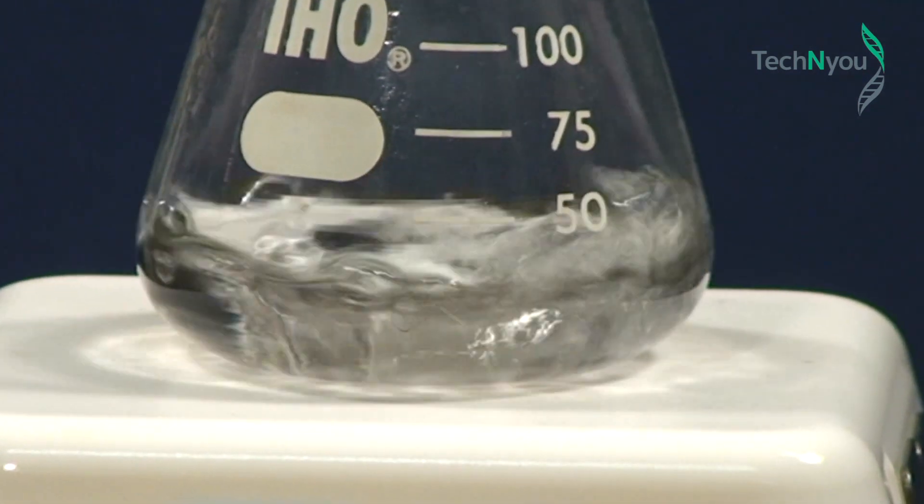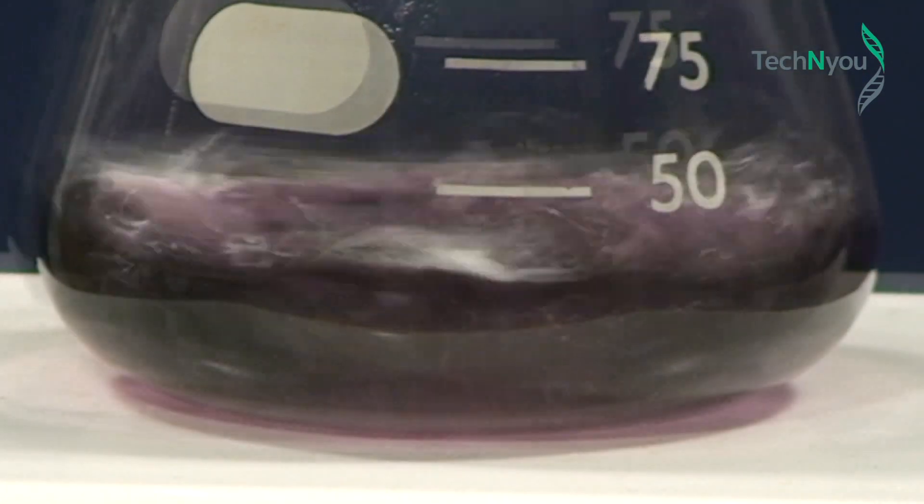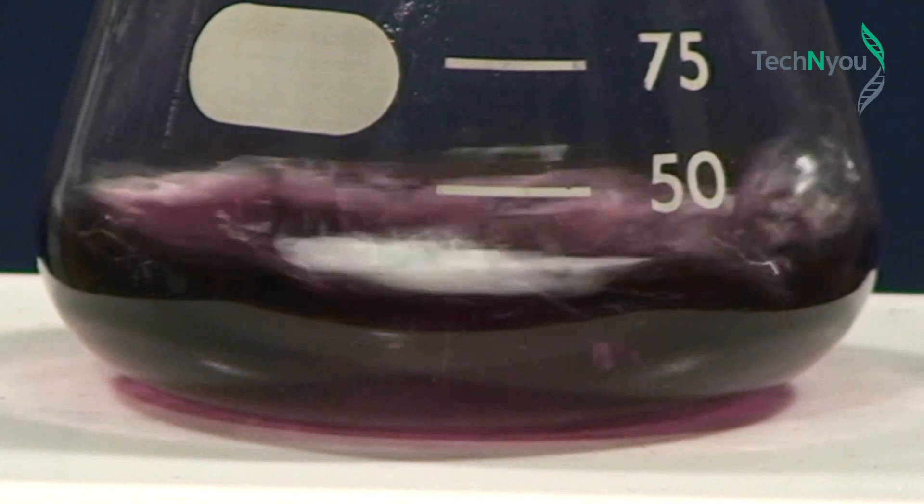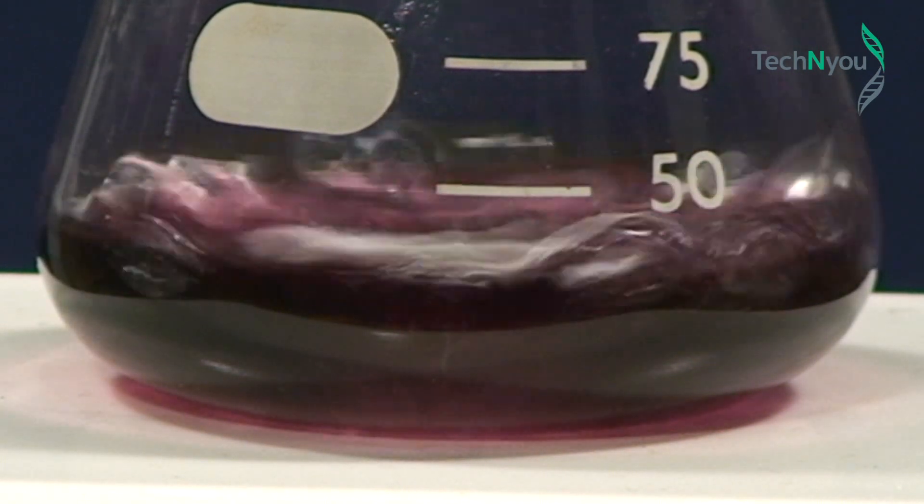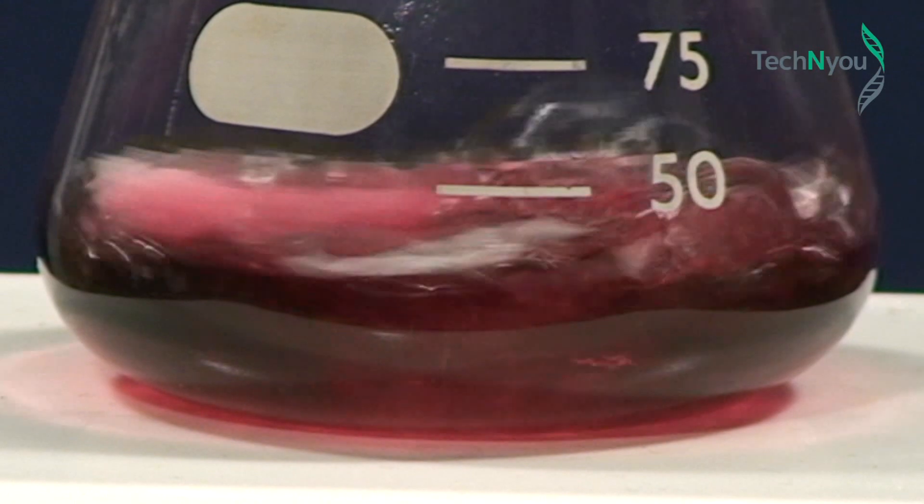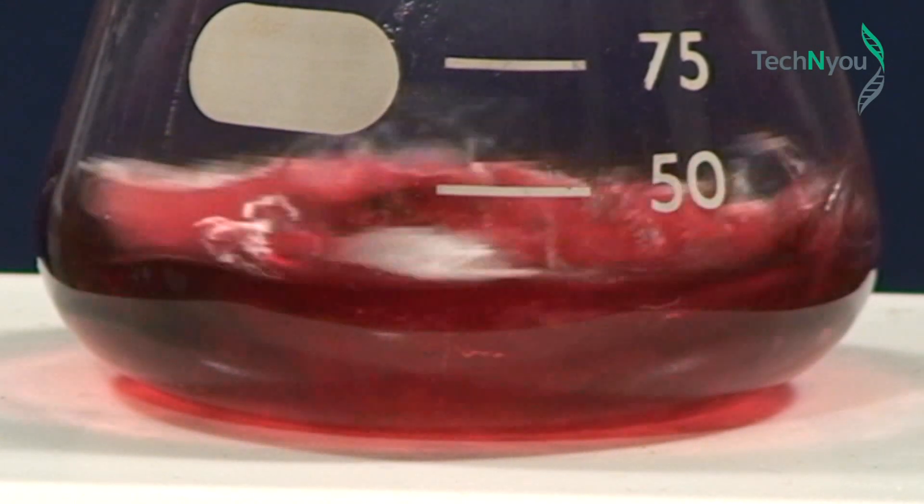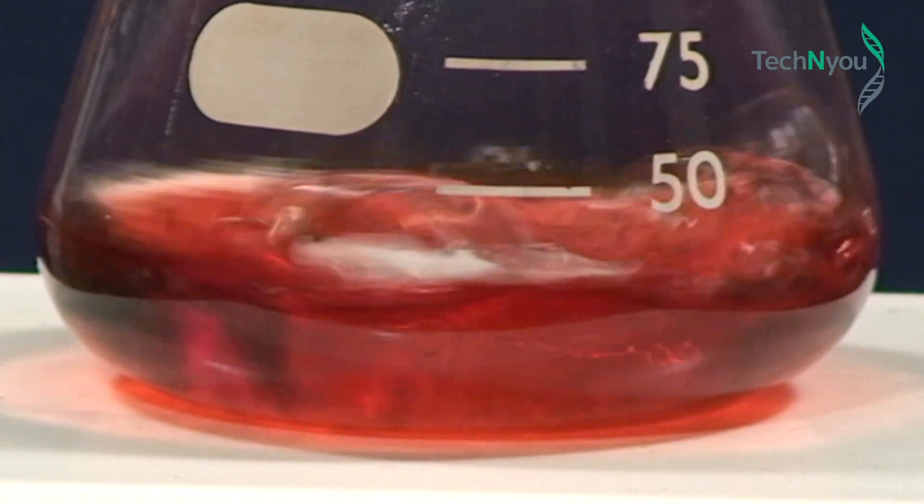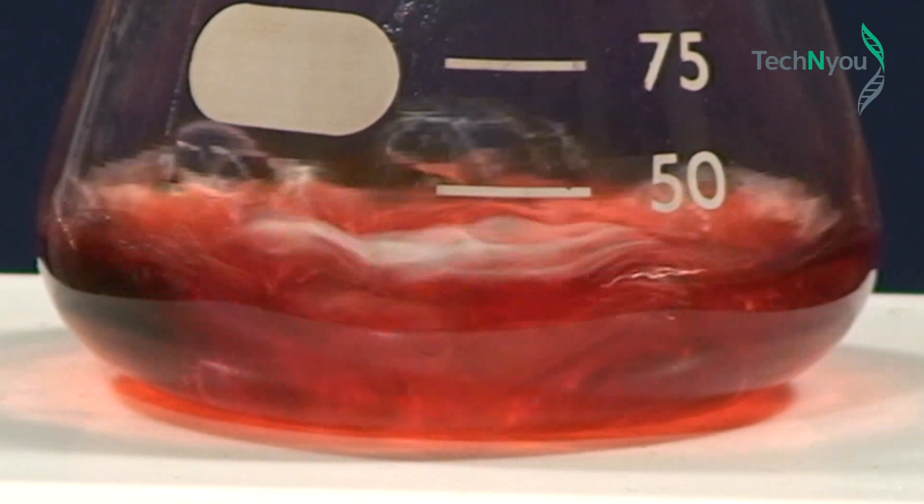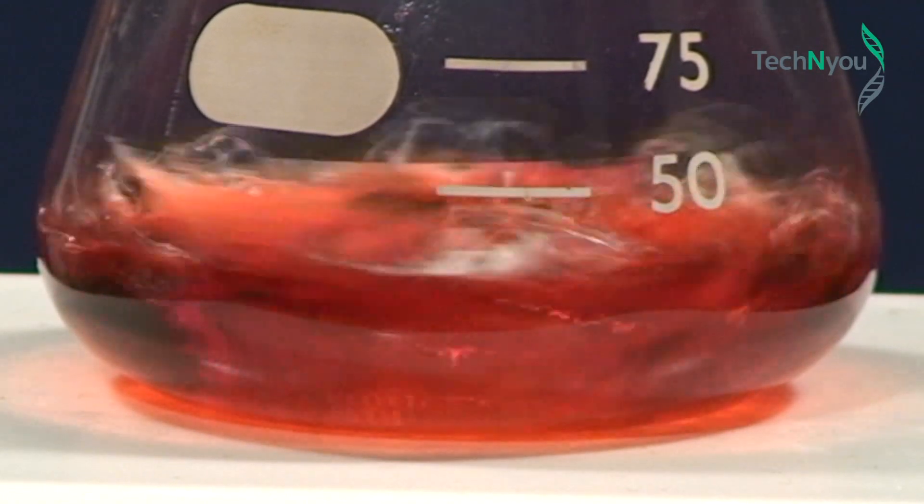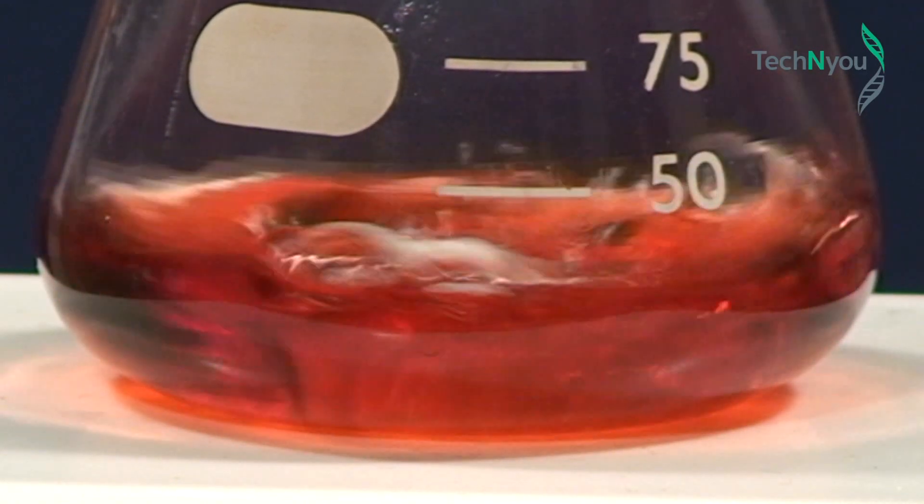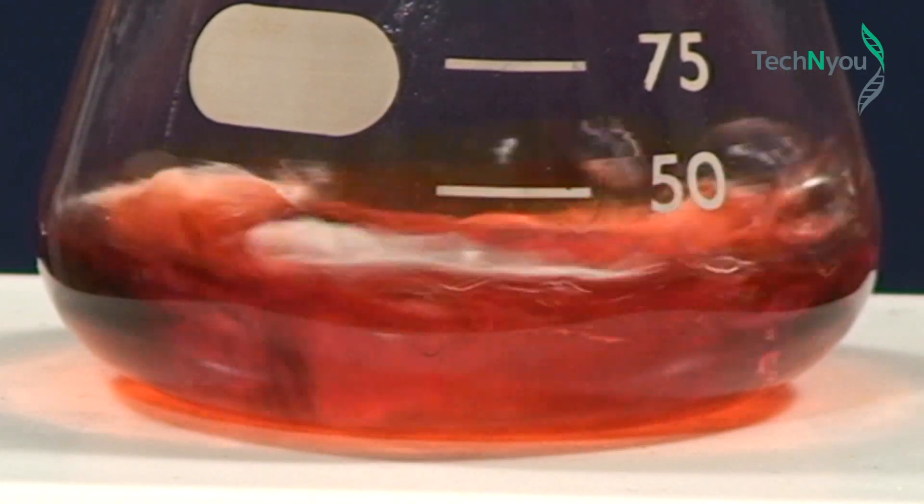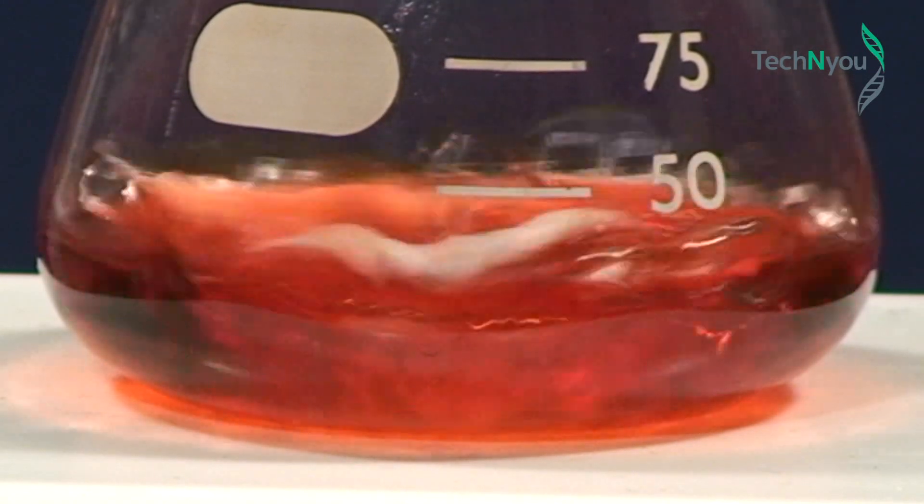You can see the color change. It's gone from light gold through a blue color phase. As we continue stirring, you can see the color change again to bright red. The red color indicates that we have produced nano-sized gold particles of around 10 to 20 nanometers in diameter, or colloidal gold, that is gold nanoparticles suspended in solution.